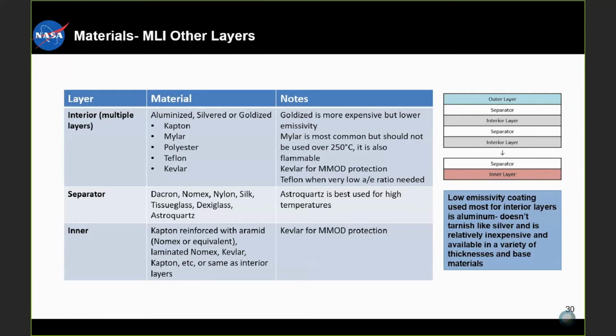And then Kevlar is used for MMOD protection, and then Teflon is used when a very low absorptivity to emissivity ratio is needed. For the separator layers, you'll see materials such as Dacron, Nomex, nylon, silk, tissue glass, Dexiglass, and astroquartz. As a side note, astroquartz is going to be best used for the higher temperatures.